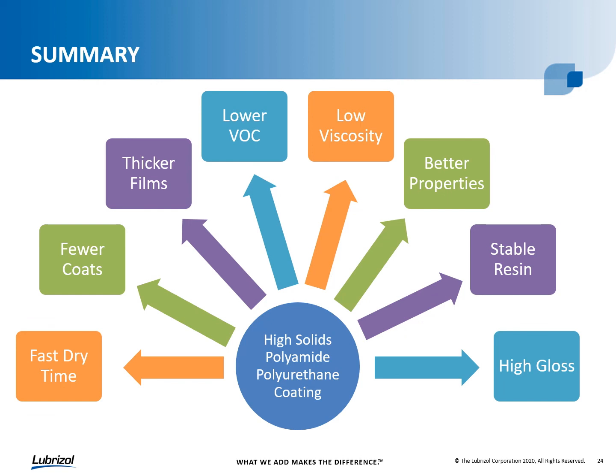Additionally, in a 2-coat as opposed to a traditional 3-coat system, it gives very good performance with fewer coats, and delivers high gloss in those applications demanding a very high gloss, high clarity finish. This coating or resin can be used clear, or it can be pigmented as well, and as I mentioned earlier, with some surface modifiers or matting agents, you can bring the gloss down for a range of different finishes.